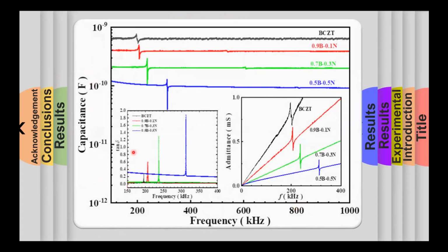Here we see the variation of capacitance, loss tangent, and admittance in the frequency domain. Prior to these measurements, the samples were electrically poled at 3 kilovolts per millimeter for around 30 minutes. Of course, because the piezoelectric phase is decreasing, the capacitance value decreases. But the more interesting observation is the resonance behavior exhibited by capacitance, loss tangent, and admittance. These resonant peak values lie between 200 and 400 kilohertz. Therefore, these resonant peaks correspond to the electromechanical resonance in the piezoelectric phase, because if the peaks were observed in the gigahertz range, they would be the ones that belong to the magnetic phase. So these resonance peaks basically correspond to the electromechanical resonance in the piezoelectric phase.